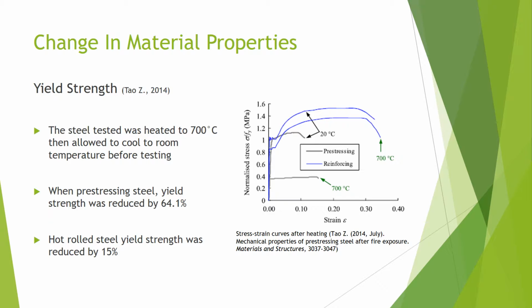When pre-stressing steel, yield strength was reduced by 64.1%. With hot-rolled steel, yield strength was reduced by 15%. This is shown in the figure.